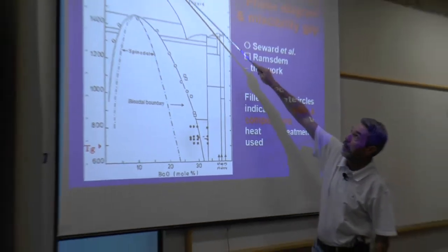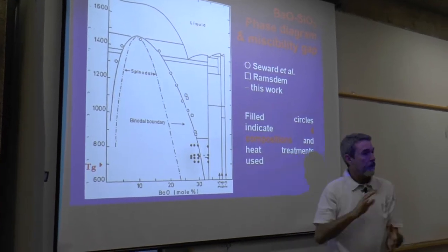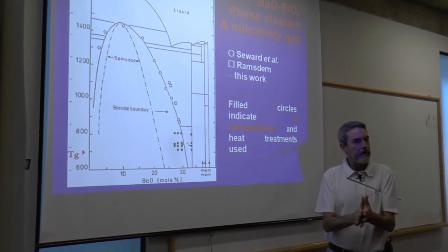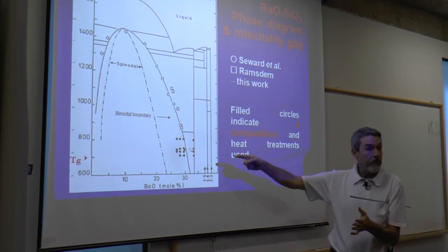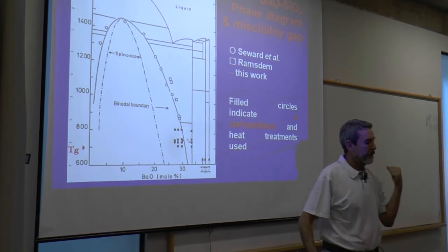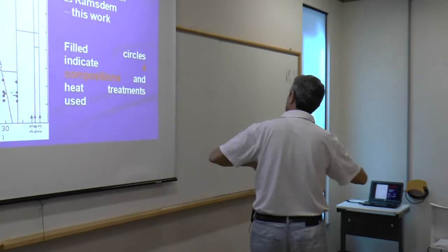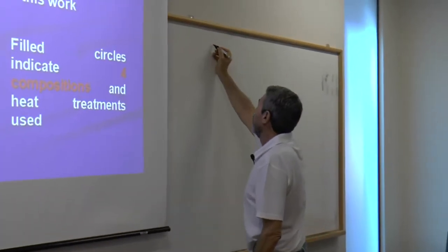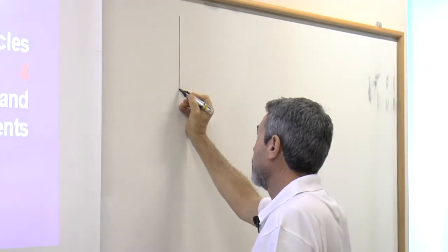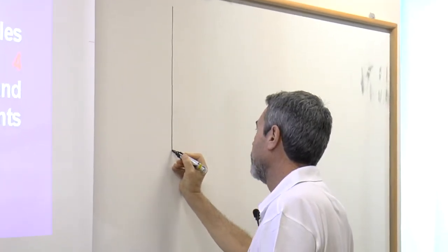We make a homogeneous glass up here, and then quench very fast between two steel plates so as to avoid or minimize phase separation. And then we heat it up here and see what happens. And then very interesting phenomena happen when we heat this up.